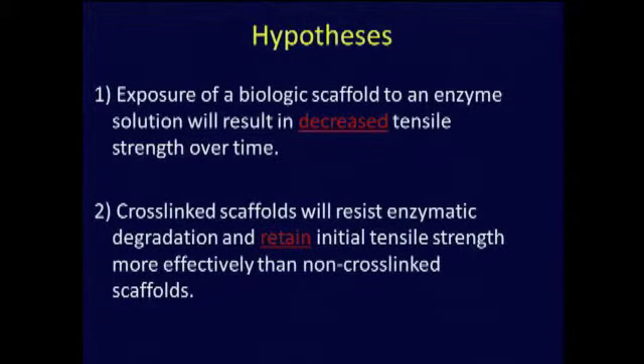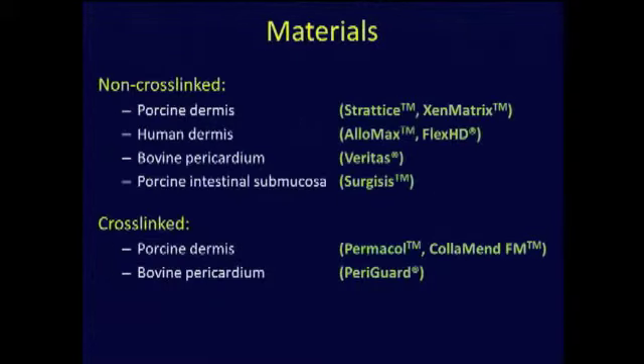Our hypothesis is that exposure of biologic scaffolds to an enzyme solution will result in decreased tensile strength over time, a decrease in tensile strain, and also a decrease in modulus. Modulus is the resistance to elasticity or stretching. It is also our hypothesis that cross-linking scaffolds resist enzymatic degradation and retain initial tensile strength more effectively than non-cross-linked scaffolds. So this intentional process of cross-linking will have a favorable characteristics in the mechanical properties of the grafts.